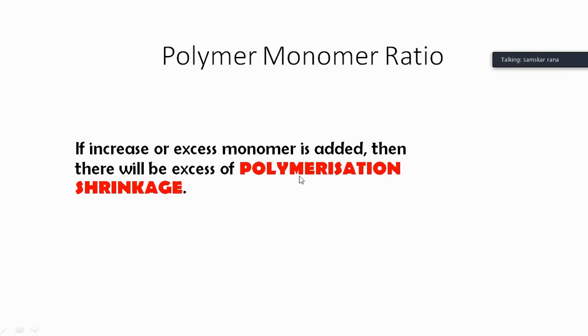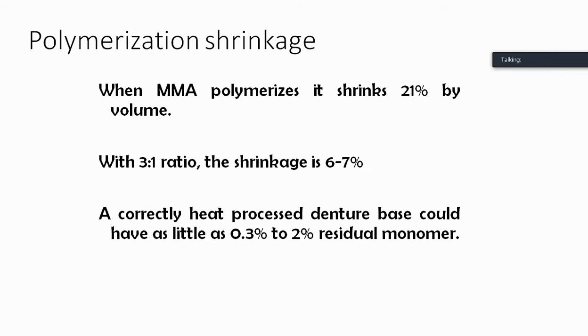There is something called polymerization shrinkage. More shrinkage will occur if more liquid is placed. So, polymerization shrinkage: when methyl methacrylate polymerizes, it shrinks 21% by volume. If your ratio is not correct, if you don't follow the formula, that is 3:1, then the polymerization shrinkage will reach up to 21%. Whereas if you place a 3:1 ratio of polymer and liquid, the shrinkage will decrease to 6 to 7%.